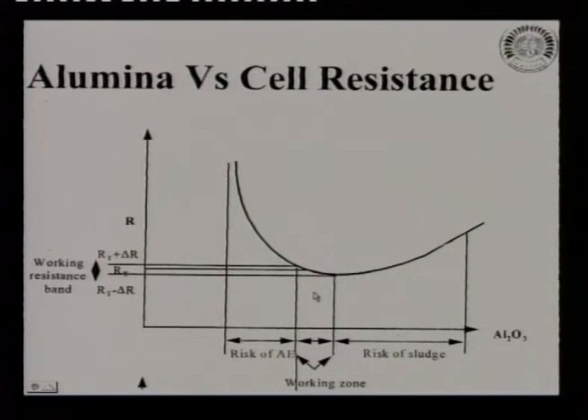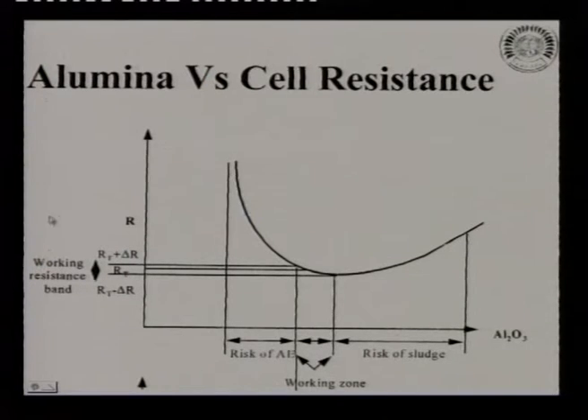If you decrease the bath resistance too much by bringing the electrodes too close, then there will not be sufficient heating of the electrolyte. If you increase the resistance too much, you will get into a lot of problem, because you might get into operational difficulties. Similarly, alumina, you see the alumina versus cell resistance. If the alumina falls too far below a limit, you will have what we call anode effect. Some gases cover the anode and aluminum cannot be deposited.